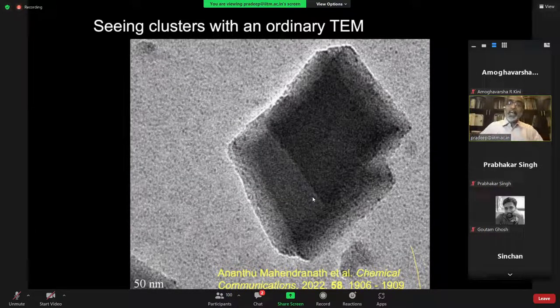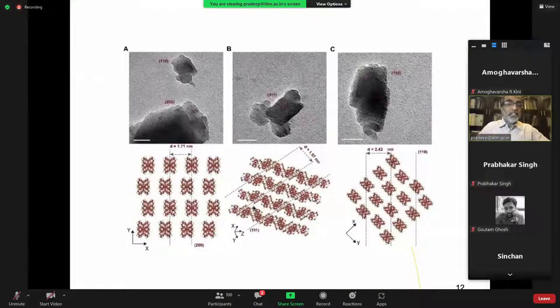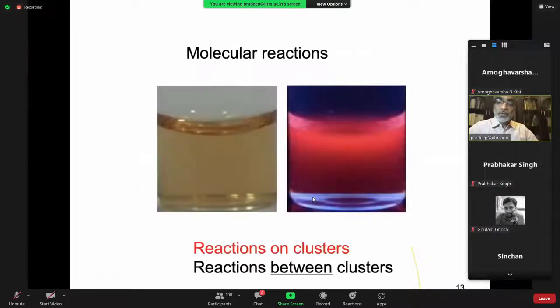So you see atomically precise clusters, this crystal lattice, and you see specific lattice planes. Now, these are the lattice planes that you see as far as gold 29, ligand 18 is concerned. You can measure this for several seconds under this kind of a condition, then of course it starts aggregating, etc. So crystals or cluster lattices are there.